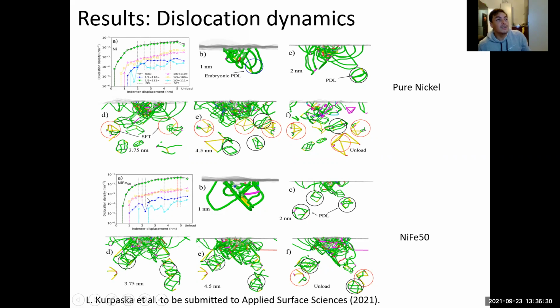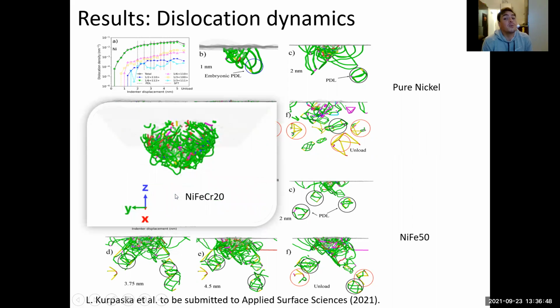This is also observed here in the dislocation density as a function of the indenter displacement, that you have the formation of the prismatic dislocation loops, but then there is nothing, and you have the stacking fault tetrahedron here at 4.5. And what is happening when you have nickel, iron, chromium 20%? This is the maximum indentation depth, and there is no propagation of the dislocations. Even there is nothing formed, no prismatic dislocation loops, nothing. So this is the reason.